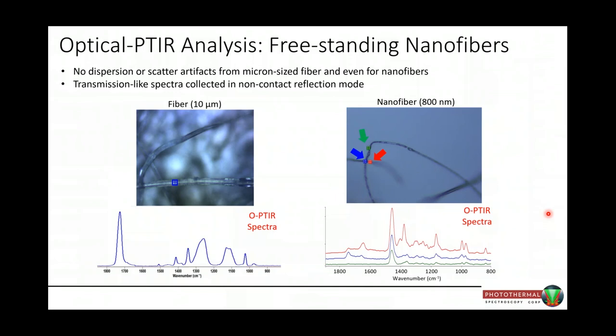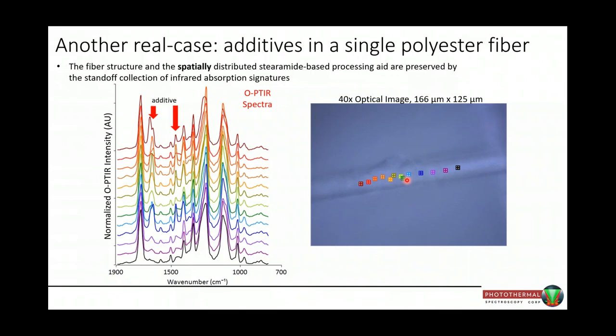Here's an example of a little bit bigger fiber, but we're able to go on the surface of it. It's a PET fiber that has an additive slip agent added, a stearamide, and we can examine various spots on the surface and see where the additive is occurring on the fiber sample.